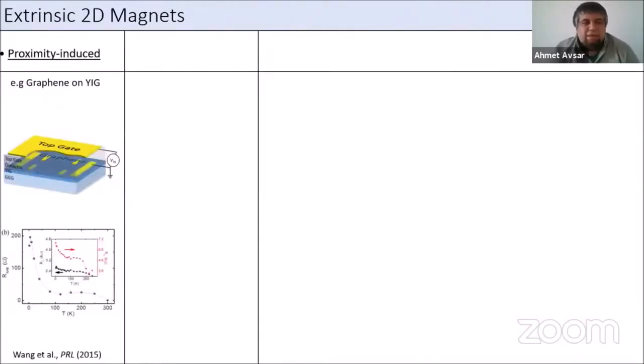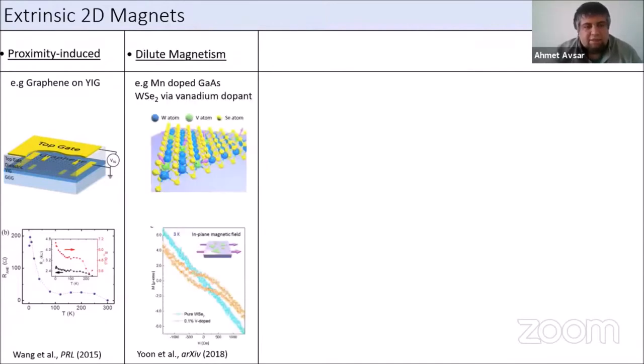Okay, and indeed, these are not the only magnets that we have. The materials that I just showed you are intrinsic magnets. And indeed, you can also extrinsically induce magnetism in 2D materials as well. So one of the methods is called proximity-induced magnetism. What you do is you get a non-magnetic material, and then you place it on top of a magnetic material. And if this proximity interaction length is larger than the thickness of the material, then you can induce this magnetic property into this non-magnetic material. For instance, it was shown that if you place graphene on a YIG substrate, you can get the anomalous Hall effect in graphene.